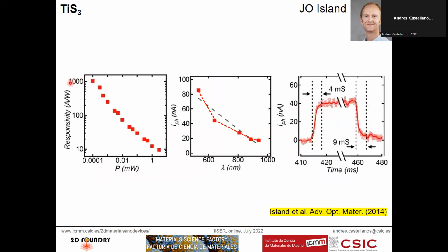Nicely enough, this material presents large enough responsivities in a broad range of the spectral range, up to 1000 nanometers basically, and is fast enough. So it has a good trade-off between all the different parameters, okay? Because it has photogating, but the detrapping time is fast enough, and it has a narrower bandgap than molybdenum disulfide. Maybe the only drawback of this titanium trisulfide is that it's an N-type semiconducting material, a strongly N-type. So it's difficult to use it for a PN junction, for example, if you want to fabricate a diode, a solar cell, or if you want to make some logics.